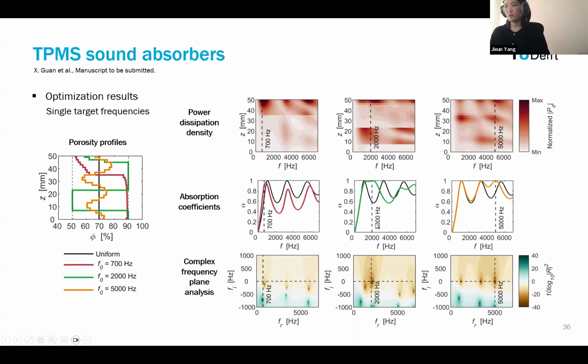And for the 2000 Hz, you have this jumping porosity again. And for the last one, 5000 Hz, you get this curve that is somehow similar to a sine wave. And to understand it better, we also drew this power dissipation density inside the porous layer. So how to read this graph is that you pick one line, and this red color means the power dissipation density at each point inside the porous layer. So for this line, the dissipation is usually happening on the top part of the porous layer, and not really much going on inside the bottom side of the layer.